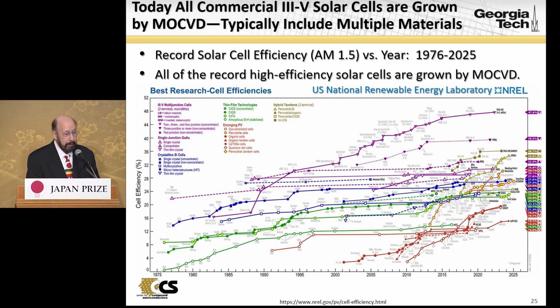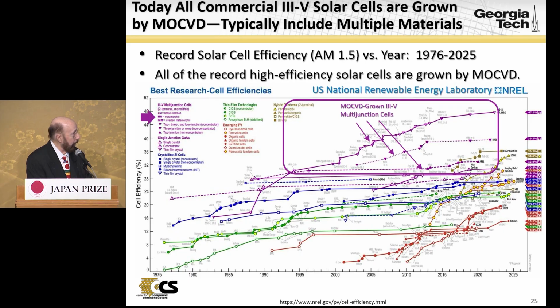Today, MOCVD is the dominant technology for all III-V compound semiconductor solar cells. This is a plot of the record solar cell efficiency at air mass 1.5 versus year for this approximately 50-year period, 1976 to 2025. Maybe hard to see, but this is III-V multi-junction cells, single junction gallium arsenide cells, crystalline silicon cells, thin film technologies, emerging PV, and these are hybrid systems. What you notice is that, I hope you can notice, all of the record cells today are MOCVD grown multi-junction cells. There's nothing that even comes close.